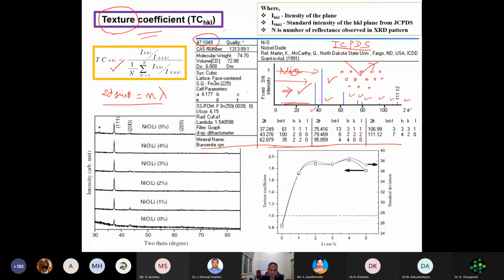So this is a standard material, and this is my film, which I have deposited using a spray pyrolysis technique. Now, if the same cubic structure is found in my material, how do I identify that? I have to take a pattern for my different films, identify the location of my 2 theta and the intensity, and then compare whether the position and intensity match. In this standard nickel oxide pattern, the highest intensity peak is around 43.2 degrees, 100%. So this is the 100% peak.